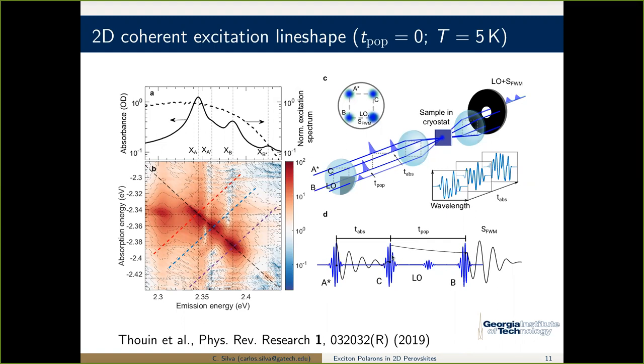You drive the system again, but now you've got an interference effect of that polarization, a grating that you set up, all of which is oscillating coherently. Then you wait and you come in with another pulse that scatters off the grating into a particular phase-matched direction, as long as you haven't dissipated that coherence. And so you can spectrally resolve this coherent emission, the third-order coherent emission from the sample that is phase matched. And through a Fourier transform measurement, you also spectrally resolve the excitation by these two pulses, the setting up of that coherent grating. This gives you a two-dimensional electronic spectrum as a function of, let's say, pump-probe time, between the excitation and that coherent emission.